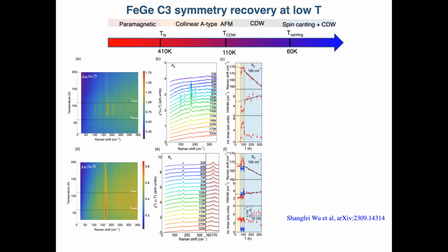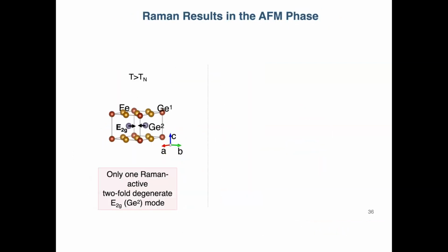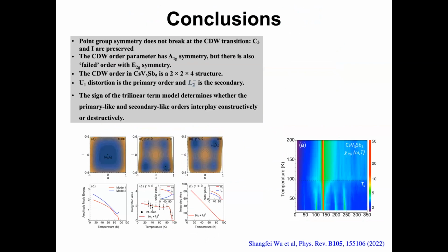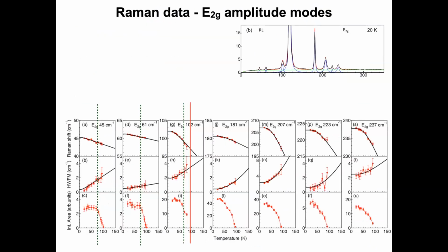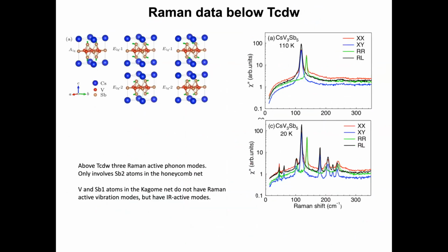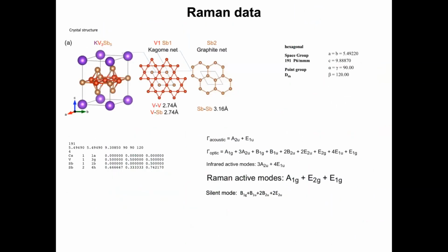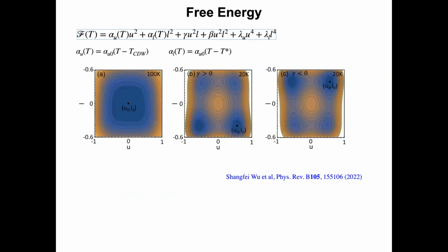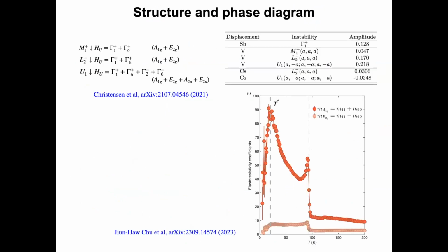Very nice talk. So I have a question. When you say this strain can induce, let's say, time reversal symmetry breaking, and that's what also Philip Moll was trying to show in the recent paper. We actually have done strain experiments where we can apply homogeneous strain on the cesium compound, and we don't see additional enhancement of the magnetic signal. Whatever we see at the ambient strain, we see the same under strain. But what we see is when you go to the surface, the signal increases by a factor of 5.